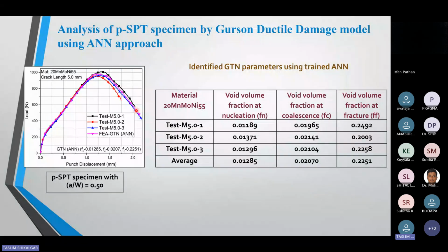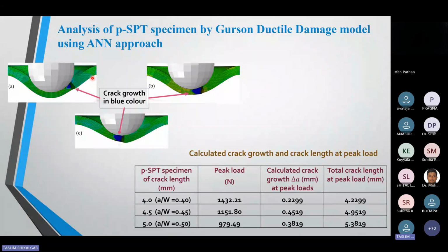So my next task is how we can use these numerical simulations to get the fracture properties. During these simulations, this is the 4 mm specimen, this is the 4.5 mm specimen, and this is the 5 mm specimen. Here you can see my damage mechanics model gives me the blue color, which is the crack growth observed during the simulations. So my next task is how I can calculate this crack growth data at the peak load.